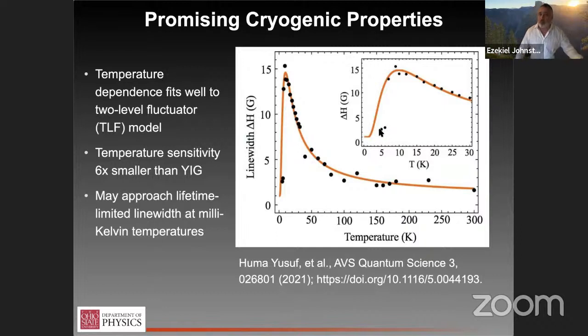And assuming no new physics crops up, and we don't anticipate any, but you never know, as we continue to millikelvin temperatures, we believe that there's a good chance that we'll see the lowest damping ever measured in a magnetic system. We expect to see another factor of 5 to 10 decrease in the damping and may even be approaching lifetime limited line widths for the magnon excitations, which would be really sort of a cavity QED type regime for those magnons. So as promised, I will stop talking here and open the floor up for questions.